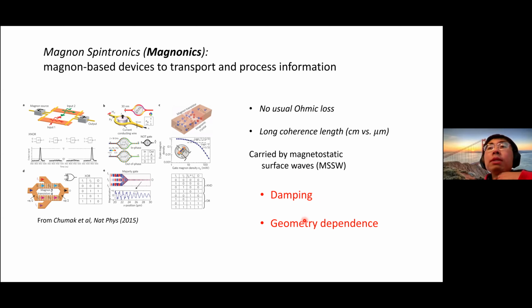The second issue is about geometric dependence, which really depends on the nature of these magnetostatic surface waves. For example, the typical large family of magnetostatic surface waves known as Damon-Eshbach modes specifically live on a surface which is parallel to the directional magnetic field applied to the system. If you look at a slightly different surface, which is not really parallel to the directional magnetic field, these waves will easily be destroyed. So it's very sensitive to the geometry of the system, which somewhat restricts the application of the surface wave in usual magnon spintronics.